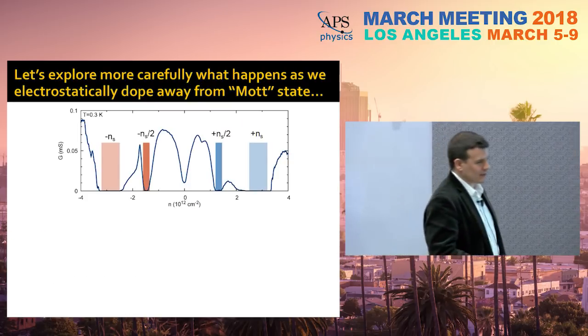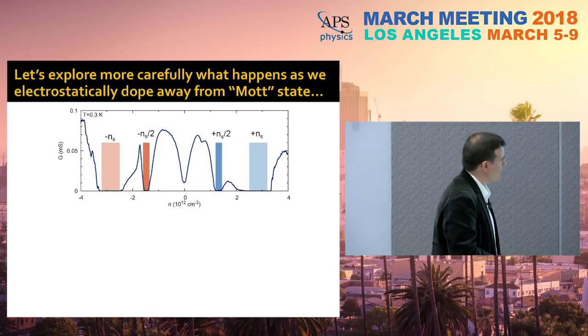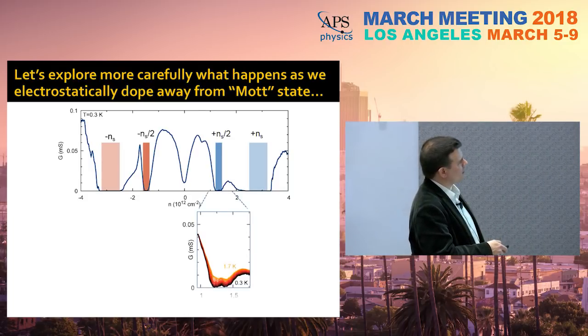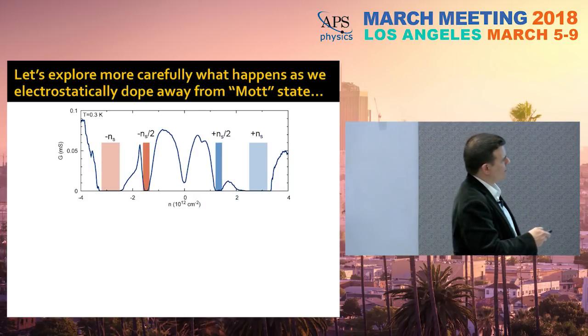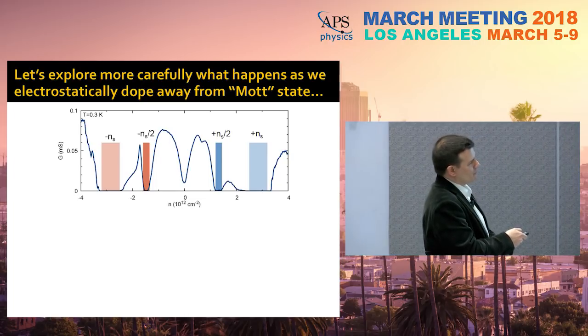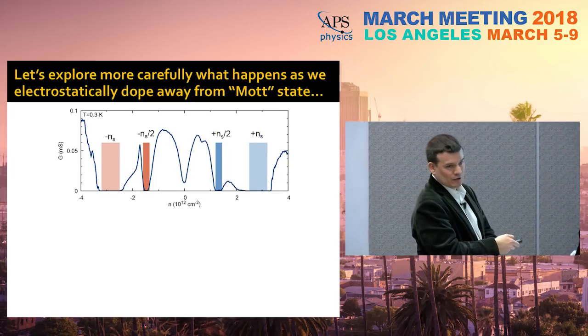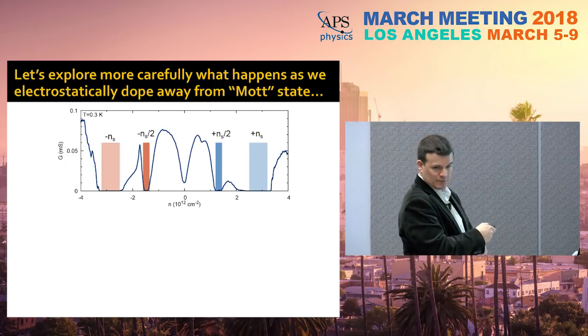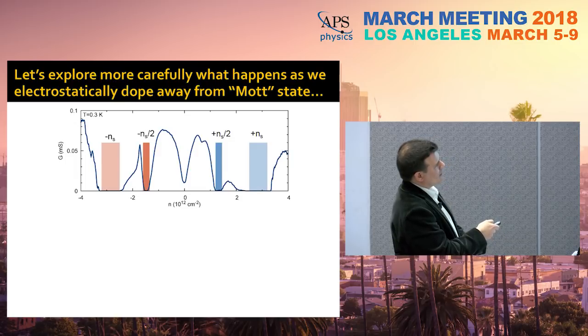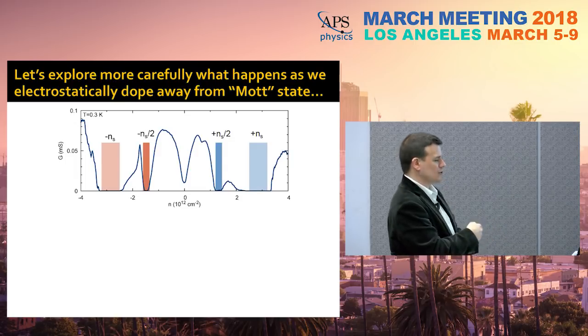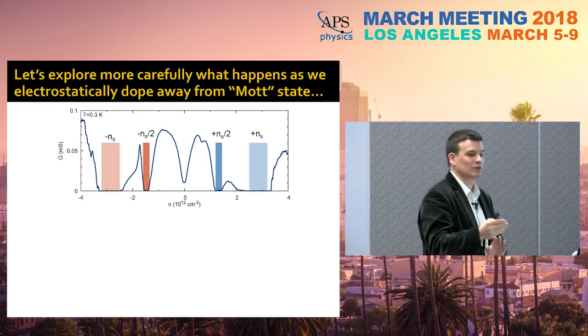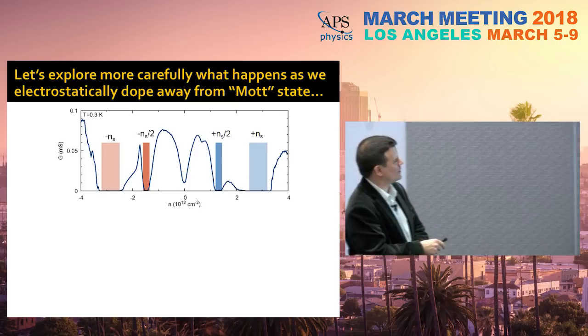When we took this data, these were two-terminal devices, okay? If we look at the temperature dependence here near, and let me remind you, from 0, if we go in this direction, we're putting electrons in the system. If we go in this direction, we're putting holes into the system. By the way, notice that sometimes we have extra features at 1/4, which I will show later, at 1/4 filling rather than 1/2, also at 3/4 filling. There's a lot more than what I'm showing.